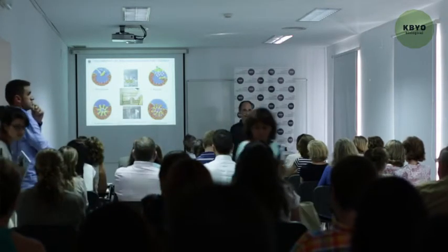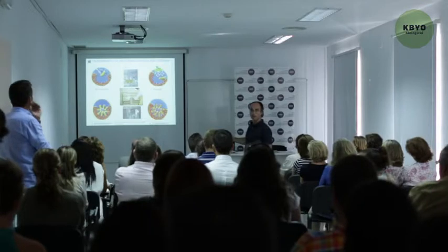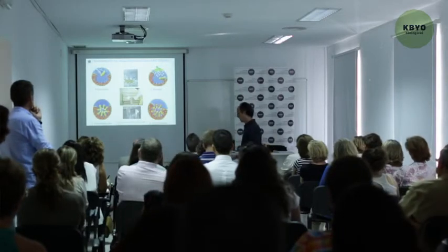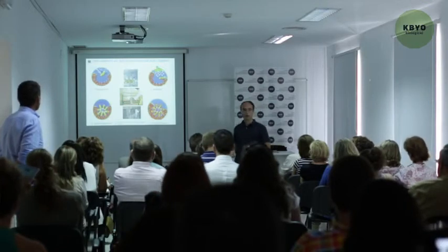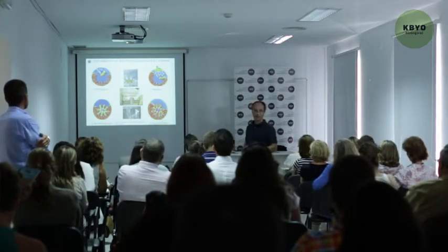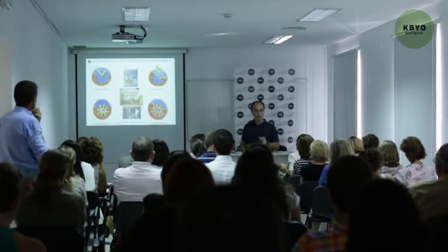Here we have the example of the external zone of San Jerónimo's monastery in Granada. It was constructed of a limey rock, where we applied treatment in some areas by pulverization of culture medium. In other cases, we applied even additional bacteria, and once the material is treated, it is covered. For 6 or 7 days, we keep it humid. Then it is covered to prevent fast evaporation by the sun effect. After 7 days, we obtain results.